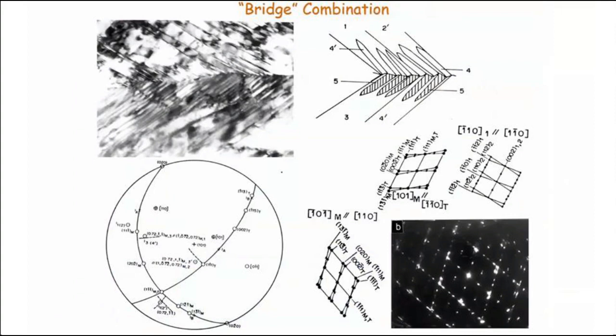here, if I go across, I'll show you the bridge combination. This I told was the most undesirable but necessary situation where both of them are not twin related, and you have this O1 twin, as they call it, forming. It stitches both the variants together, something like a zipper, and this also forms a twin interface which can revert back to the original grain.